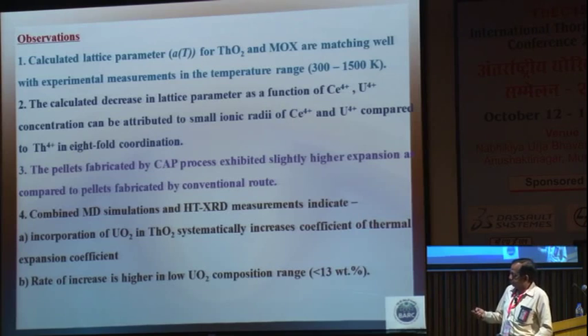Calculated lattice parameters of thorium oxide and MOX are matching well with experimental measurements in the temperature range 300 to 1500 K. The calculated decrease in lattice parameter as a function of the concentration of these two species can be attributed to the small ionic radii of these species as compared to thorium in 8-fold coordination. The pellets fabricated by the CAP process exhibited slightly higher expansion as compared to pellets fabricated by the conventional route.